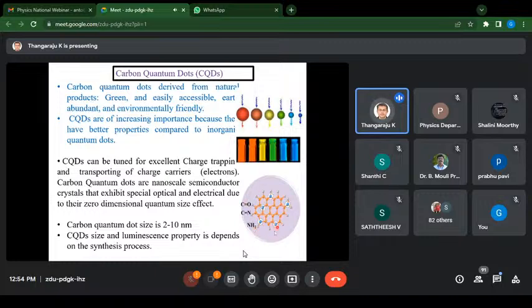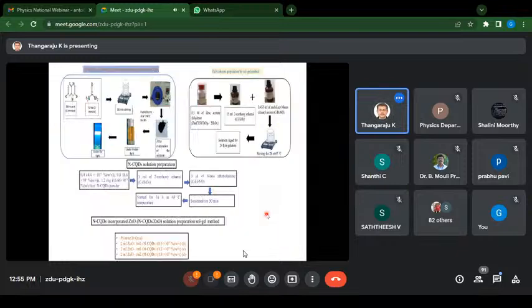So you can see the advantage of carbon quantum dots, as already mentioned in the previous talk, that they will have a large number of defects and surface functional groups. So the presence of surface functional groups and defects will give you efficient absorption of the UV light, and help transport the UV energy to the zinc oxide. So this is the typical processing steps involved to produce the carbon quantum dots, and the processing of the carbon dots zinc oxide based hybrid thin films by this solution process method.